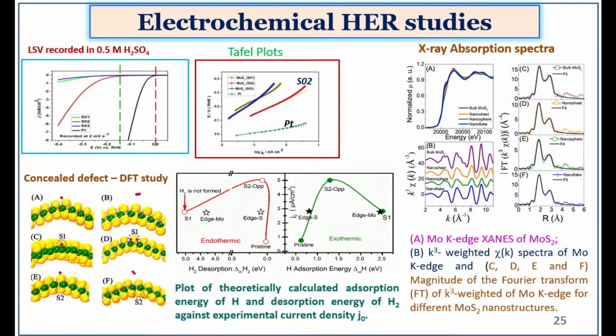So that gives more active edge sites, where one of our friends helped us to calculate the hydrogen proton adsorption and hydrogen desorption energy on S02-based structures, and they found that the active centers are especially the edge sites. S02 gives a very low adsorption energy for the proton, and similarly a very low energy for the removal of the hydrogen gas which is formed on the surface. So that means it offers more active centers to adsorb the proton easily, as well as offering very easy desorption of the hydrogen gas formed on the surface. So it produces more hydrogen gas in a fraction of time. That is called the TOF, turnover frequency number. We will be seeing that later.